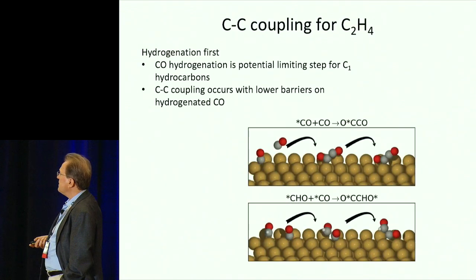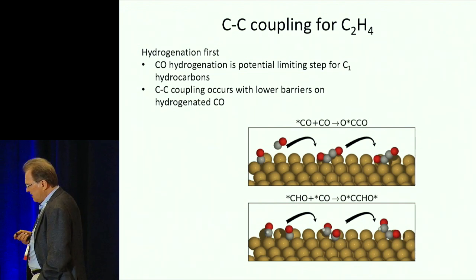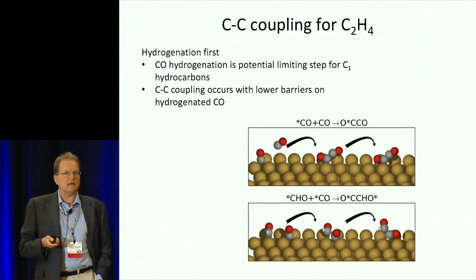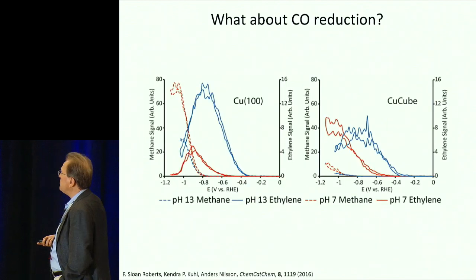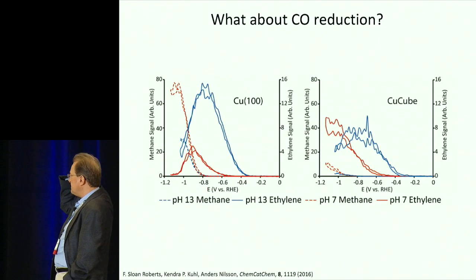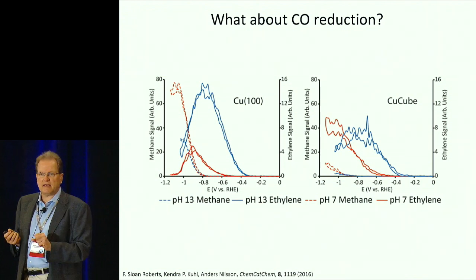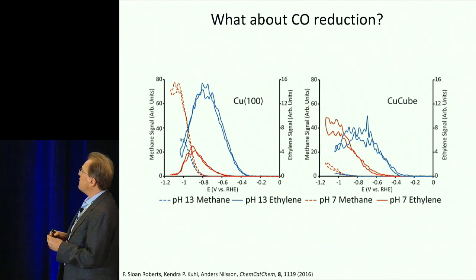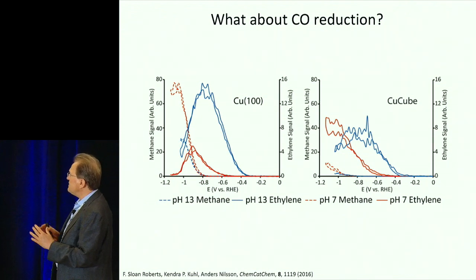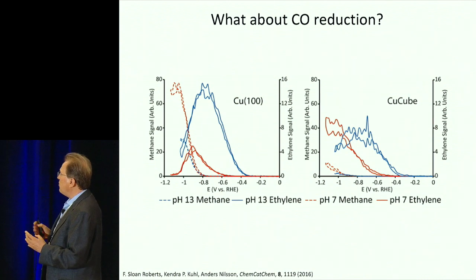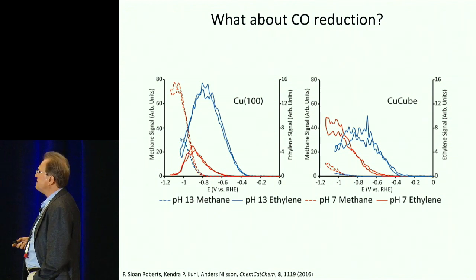And of course, for forming ethylene, C-C coupling is very important. This is an area of intense theoretical work in Jens Norskov's group to understand all this detail. We can see a similar effect also if we do CO reduction, which is something that Matt Kanan did recently on these types of systems. And we see similar phenomena at different pH, where the copper cube seems to respond to the pH change just like a single crystal, but we see this change in selectivity.